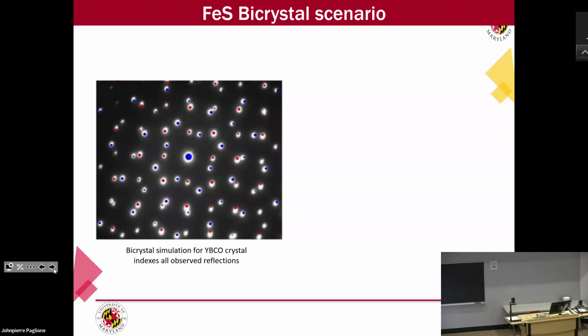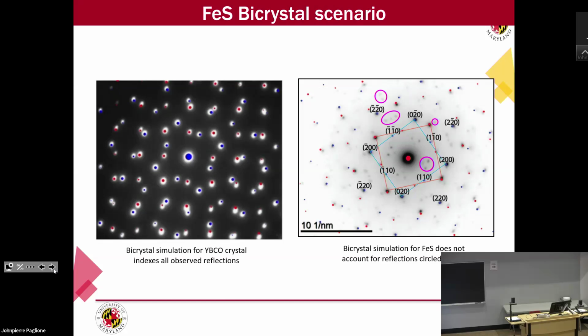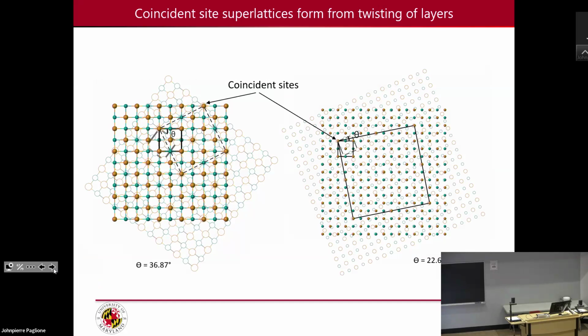One of the cool things that we found about this is that sometimes it leads to layer twisting. And so many of us are interested now in twistronics or whatever. And we're able to see this in some of our solvothermal growth. At first, we thought maybe we just had what's called a bicrystal, where two crystals are stuck together. This YBCO cuprate superconductor has that kind of behavior where you have square lattices that sort of twist with respect to one another. We tried the same for our square lattice because it's also a tetragonal space group. And we found that, in fact, in many times, even though layered materials, you think of them as just stacking on top of each other, they can actually twist. And that solvent that you grow in can help aid that. So ethylene diamine, for example, led to that.